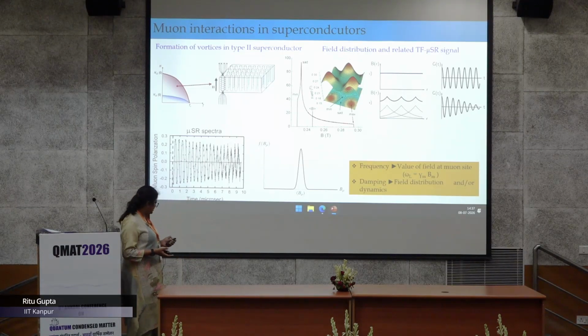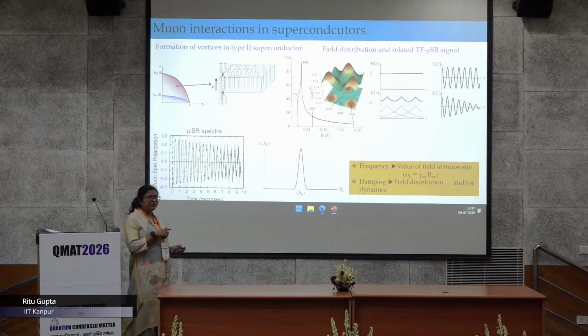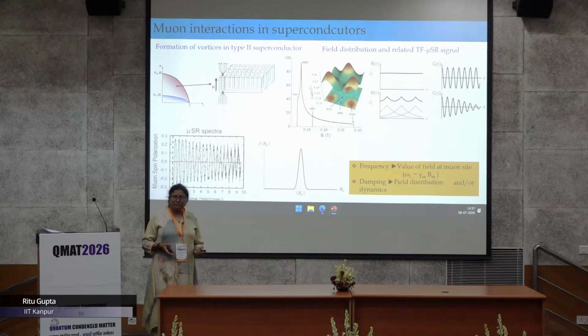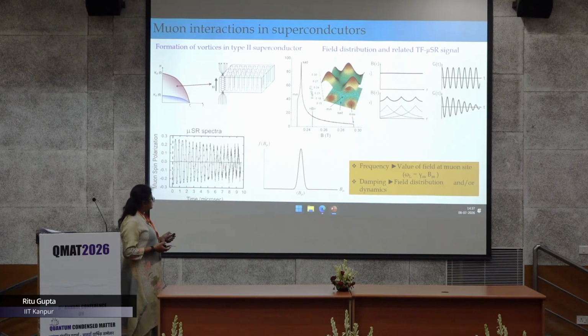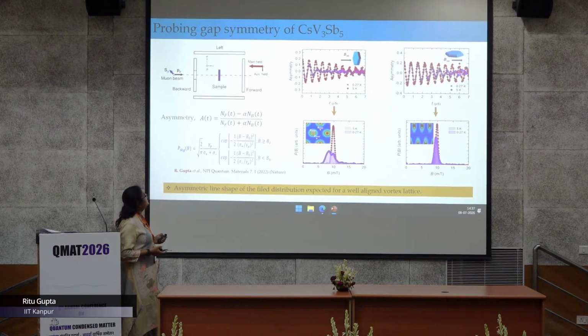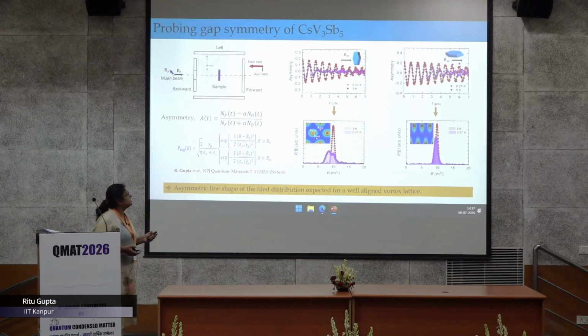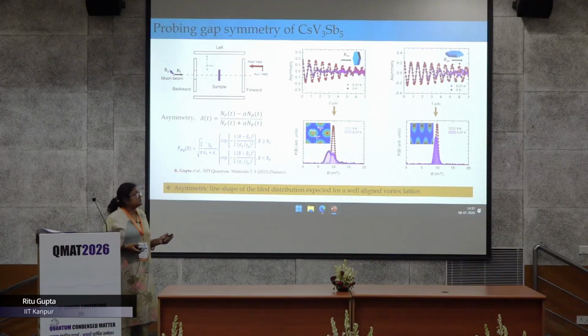So if we collect spectra at different temperatures, you have superfluid density as a function of temperature, and then you can use different models to tell which type of superconducting gap symmetry is in your system, right? So with the basics of the MuSR technique, let us move to the sample which we studied, cesium vanadium 3 antimony 5. We did experiments in two different configurations.